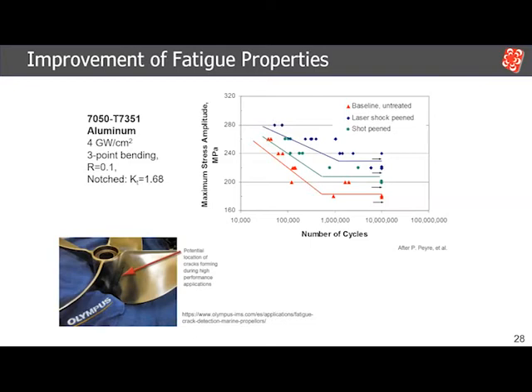A more common way of representing fatigue life data is through SN curves. You can see the same pattern: we're trying shot peening, we're trying laser peening, and they're giving better results. Laser peening is generating a higher amount of improvement. There are two ways of looking at these life improvements in the SN curve. You can take a fixed stress, let's say around 260 megapascal. The baseline is around 50,000 cycles, shot peening is around 100,000 cycles, and laser peening is at around 300,000 cycles. So at a specific stress level, shot peening doubled the life, and laser peening was able to generate around 6 times the life.